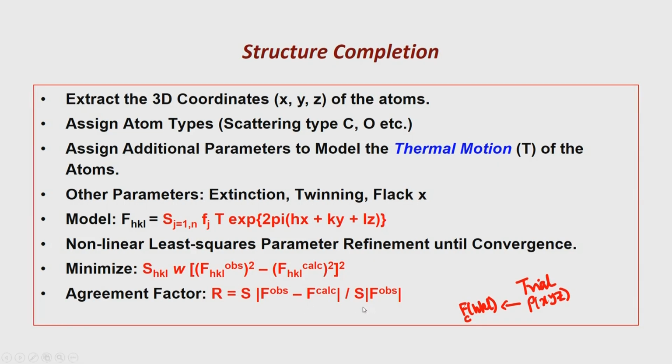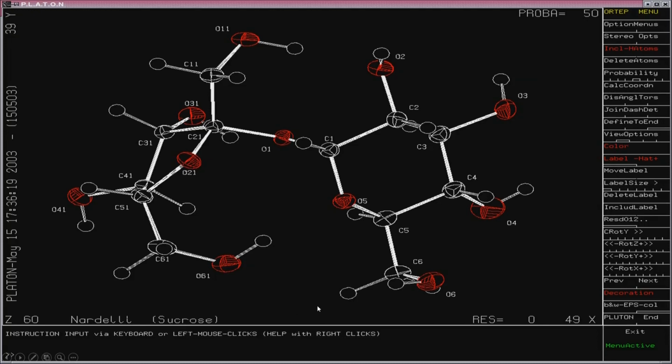So, when we do this difference Fourier plot, many of the hydrogen atoms will show up as possible small density values, around 1 electron per angstrom cube, and these positions therefore can be fixed now. We can identify their hydrogen positions, and then we see also the geometry that is associated with those hydrogen positions. In case the hydrogen positions are not coming out clearly, then one can use the stereochemical information that is available in the molecule. In case of sucrose, we know whether it is up or down, whichever way the hydrogen positions are going. We call them alpha and beta in the sucrose nomenclature.